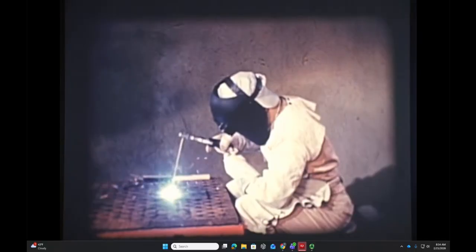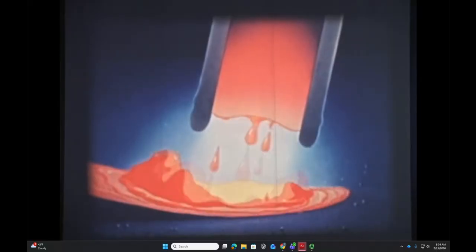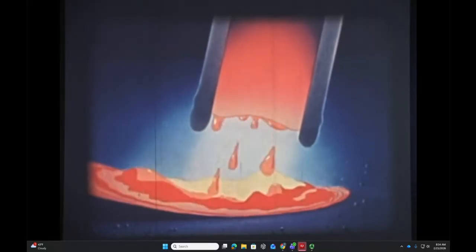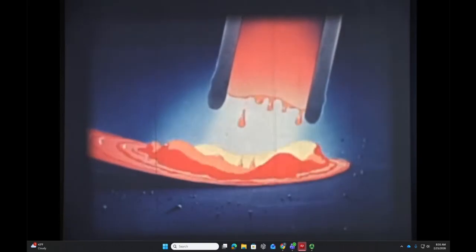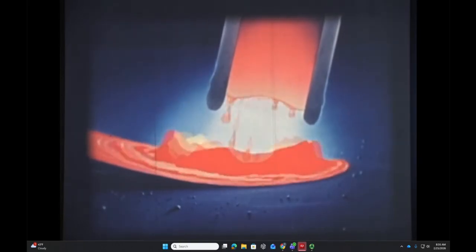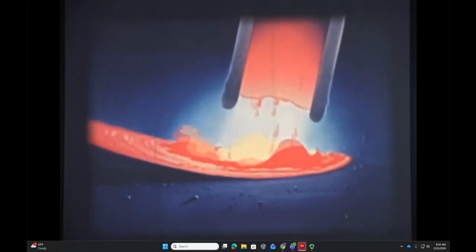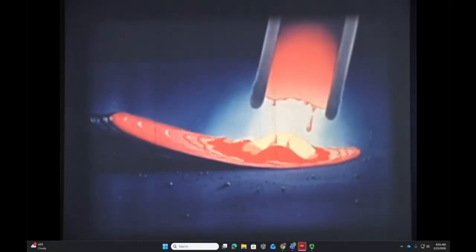Shielded arc welding is usually accomplished by means of an electric arc formed between the work and a coated metallic electrode. Let's see what happens. When the arc is struck, it almost instantly creates a temperature of about 6,500 degrees Fahrenheit. This melts both the base metal and the metal in the electrode. The metal from the electrode is melted off in tiny droplets, is carried across the arc and mixed with the molten base metal. The force of the arc and the forward travel of the electrode causes the mixed molten metal to be pushed to the rear of the crater, where it cools to form a bead.